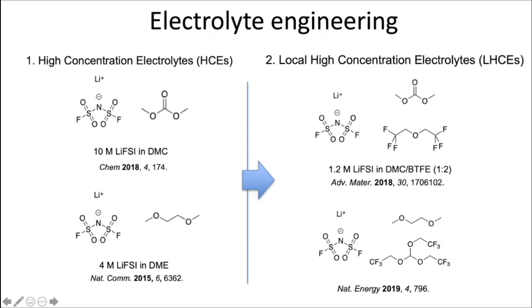So there have been a number of approaches in the literature to try to solve these issues. For example, one very promising approach is a high concentration electrolyte. So basically, using a very high concentration of lithium salt, all the solvent molecules participate in solvating the salt, and therefore their reactivity at the electrode side is reduced. And in this case, one of the drawbacks is the high viscosity of this kind of high concentration electrolyte.